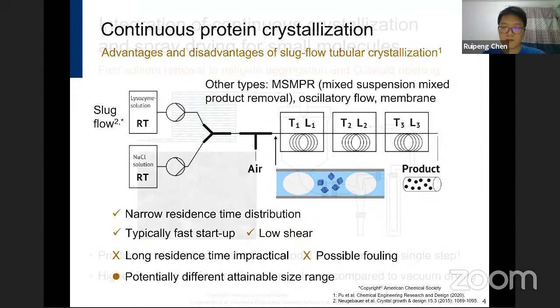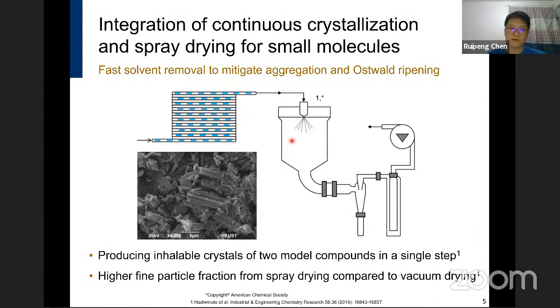So actually, in the previous work of our group, we used segmented flow crystallization to produce inhalable crystals of two model compounds. The tubular reactor was integrated with a spray dryer. Spray drying is a process which can produce a dry powder from a slurry or solution within seconds. The reason for the integration is the need for fast solvent removal to mitigate aggregation and Ostwald ripening, which is likely to occur in a suspension.